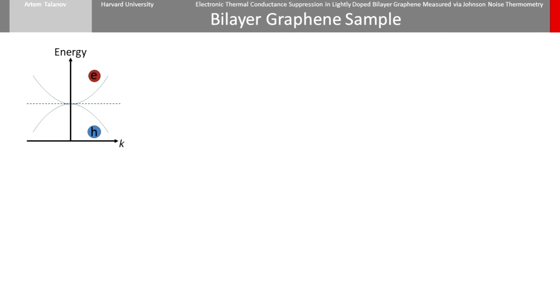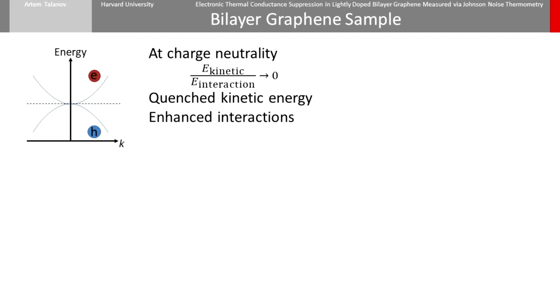In this work, I've measured the thermal conductivity of bilayer graphene. Bilayer graphene has a unique band structure with two parabolic bands touching at a single point and no band gap. This has an interesting consequence on the ratio of kinetic to potential energy, which determines how important interactions are. In monolayer graphene, this ratio is constant with respect to chemical potential, but in bilayer graphene, this ratio diverges as the chemical potential approaches the charge neutrality point.